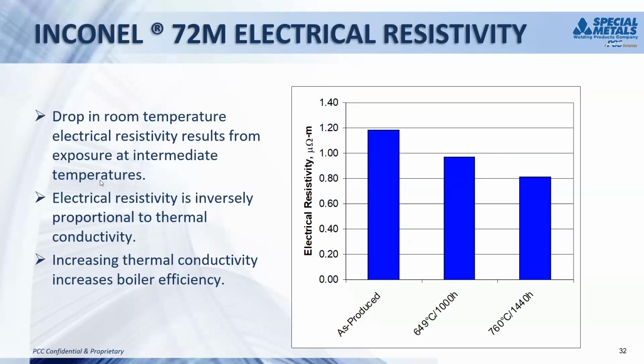Next slide. One of the last little nuances that was discovered with one of the new Inconel 72M filler metals was the electrical resistivity. Obviously, the reason we're going for these upgrades to these plants is to get more efficiency out of a given plant. So with the Inconel 72M, you actually have a very interesting phenomenon happening during the service life of that alloy. As it's deposited, you have an electrical resistivity of about 1.2, I believe that's micro ohms per meter. But as that alloy sits in service and experiences higher temperatures, your electrical resistivity actually goes down over time.